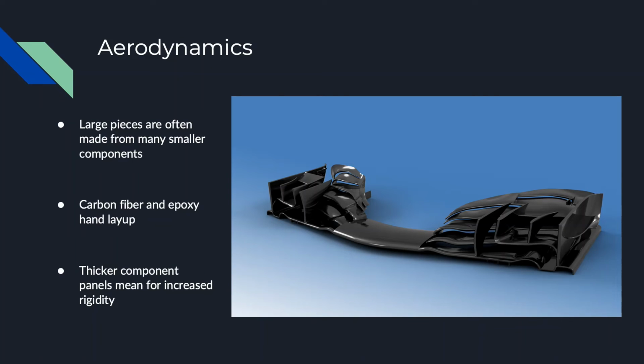Most of the larger components, such as the front and rear wings, are made from many separate pieces which are then bolted together. This makes replacing damaged parts or changing setups for different conditions much easier and more cost-effective. These smaller individual pieces are usually flat and panel-like with bends on either side for bolt holes. Most of these parts are made out of a mix of carbon fiber and epoxy, usually about 10 layers thick, and are created using a hand layup technique. This technique provides flexibility in the design itself, and the material used gives a very high rigidity with minimal weight.